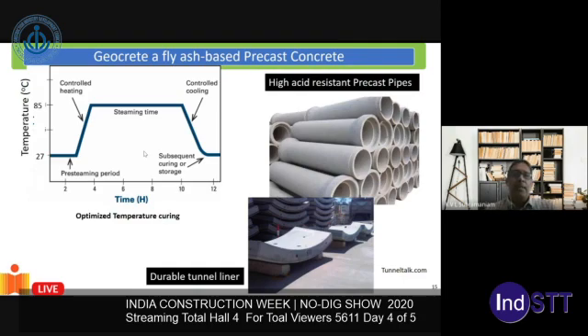So we are now looking to see if this material could be used to support infrastructure development. Steam curing can easily be adopted, and it is being done for producing a lot of construction related products. If you look at steam curing that is conventionally followed, we raise the temperature to about 85 degrees Celsius, hold it there for some time, 6, 8 to 10 hours, and then we cool down the product. This is the ideal temperature for geopolymerization to happen. We can actually accelerate the geopolymerization and deliver the strength much quicker, as I had shown before. Because these geopolymers produced from fly ash have a very high acid resistance, they are ideal candidates for making precast pipes, which can be used for sewage and even for transporting water in the urban setting.